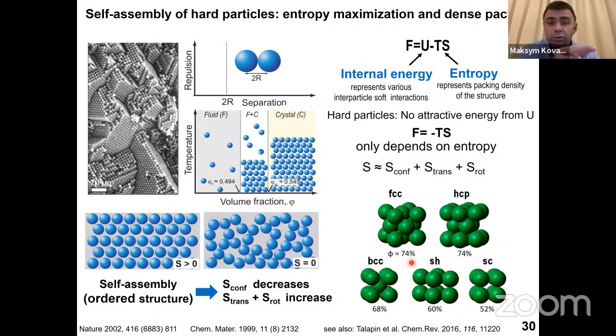They will undergo self-assembly into ordered states because at the late stage of drying, they maximize the free volume entropy, essentially. And even though they sacrifice configurational entropy, you still get an overall small entropy increase through the conversion into the ordered state at a very late stage of drying. And then the solvent evaporates fully, and you are locked into a superlattice. For spheres, you will end up with one of the densest sphere packings, which is face-centered cubic or hexagonal close packing.